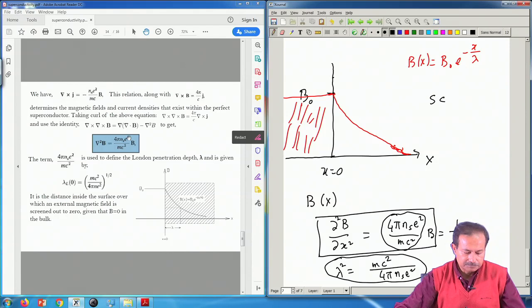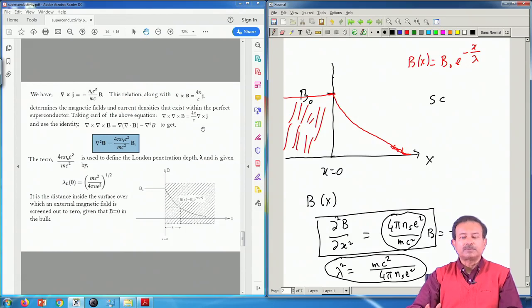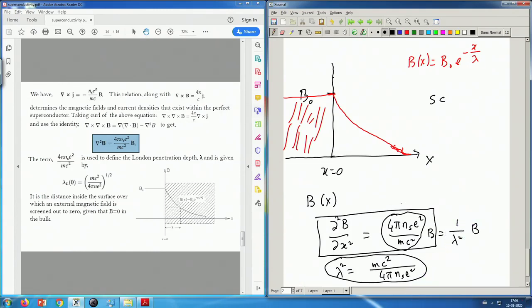So, this was the way the magnetic field going to 0, perfect diamagnetism, was explained by London's equation. Okay. And it also predicted this length scale over which this will happen, and it came out naturally. Look at this, the only thing that depends on the system here is this n_s. So, in this equation at least, the dependence is only through the conduction density of the superconducting fraction.